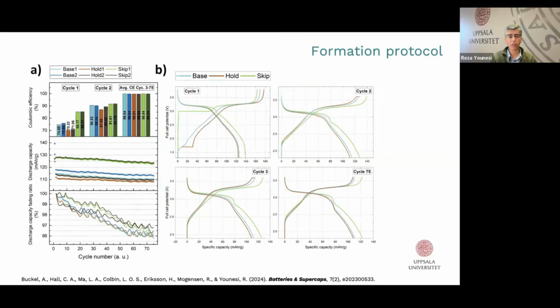Using these three different protocols, we measured the first cycle Coulombic efficiency and also the Coulombic efficiency in the following cycles, and the discharge capacity and capacity fading for all three protocols.